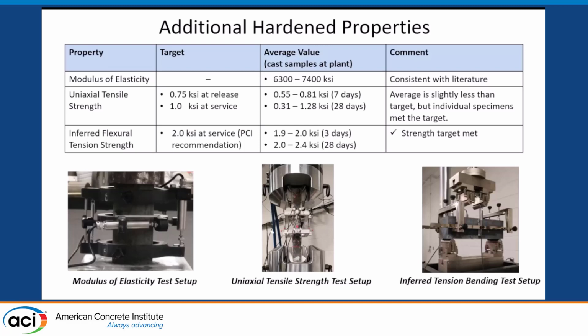So in the uniaxial tension test setup, we do measure deformations as we do in the flexural setup. This middle test, the uniaxial tension test, is a little bit difficult. I think it takes a lot of practice and lessons learned because you are testing a concrete prism in tension, and sometimes it breaks outside the area where your LVDTs are located and so on. So what we found is that on average, we were sometimes a little bit lower than our target strength, but individual specimens where we had a successful test were meeting the required strength. So we felt like we were getting reasonable results.